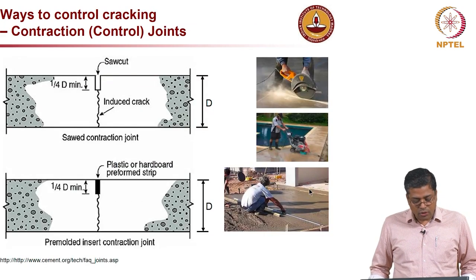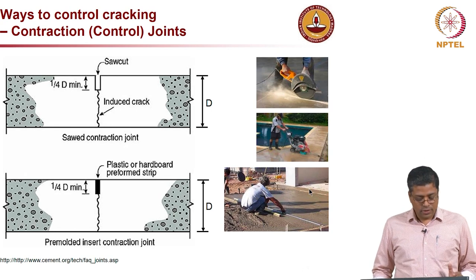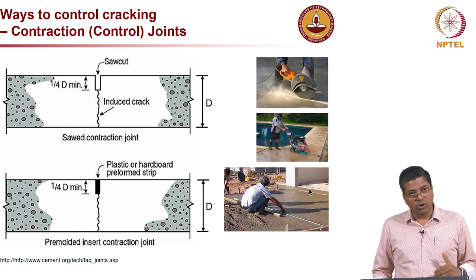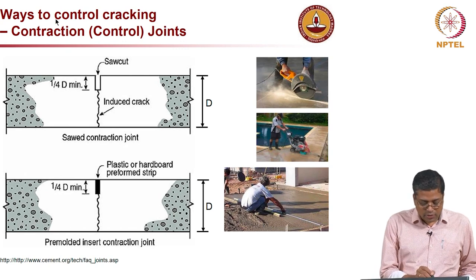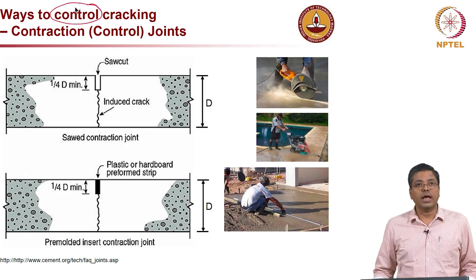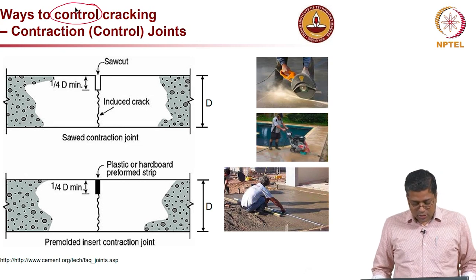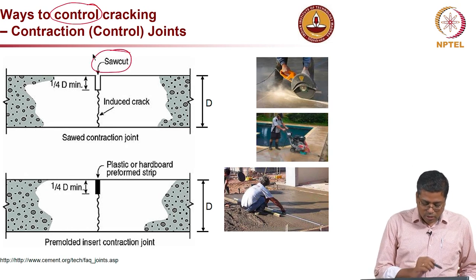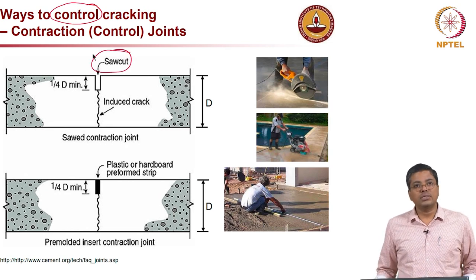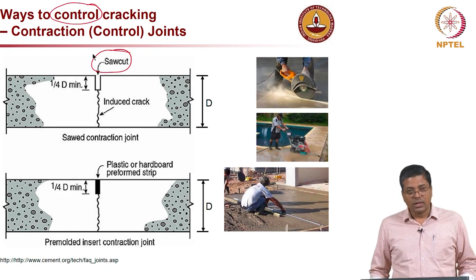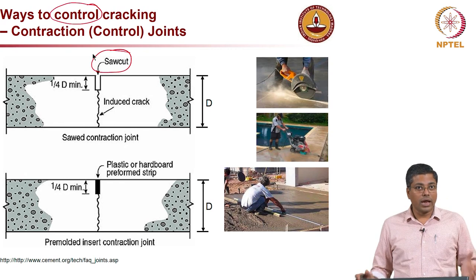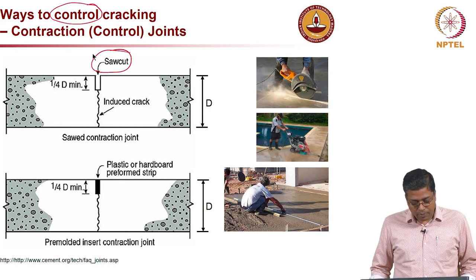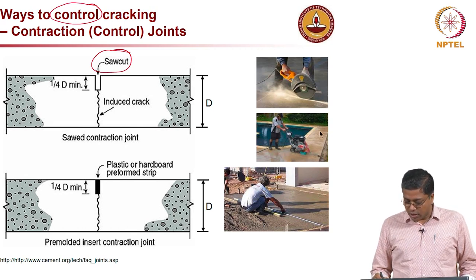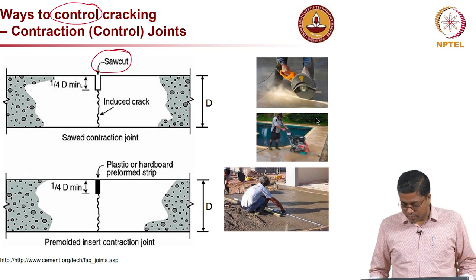And how do we control shrinkage or control cracking in concrete? And look at the word, I am talking here about controlling the crack, not preventing the cracking. So you can see on the sketch where we are providing a saw cut. If you have a concrete slab, a very long slab, then as concrete shrinks, it will lead to cracking. So it is very difficult to prevent cracking in such a case, especially for a road or highway, something like that, or slabs as you see in these pictures over here.